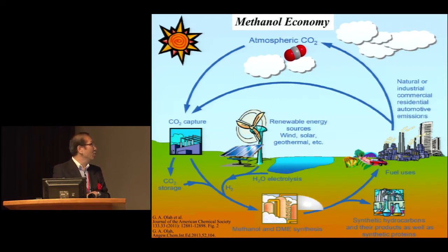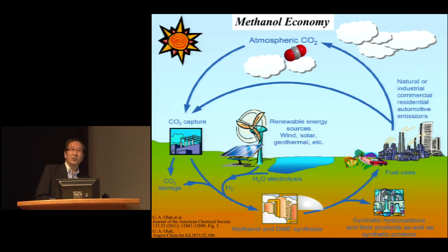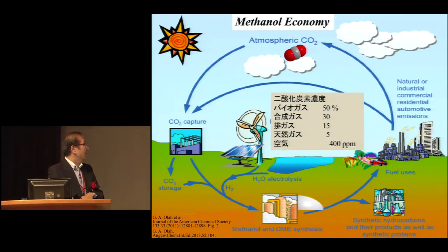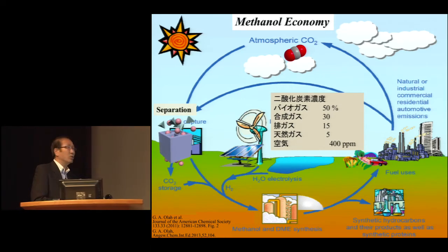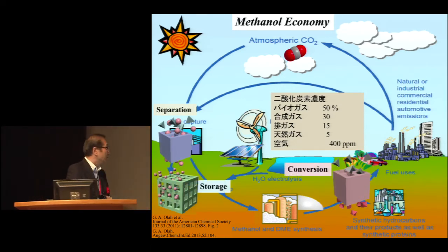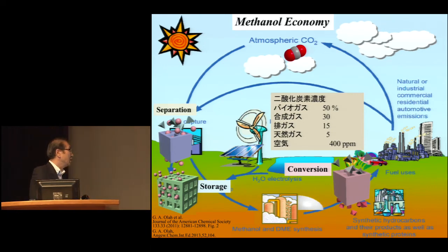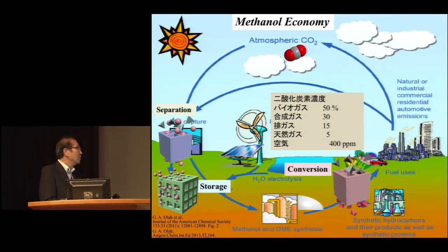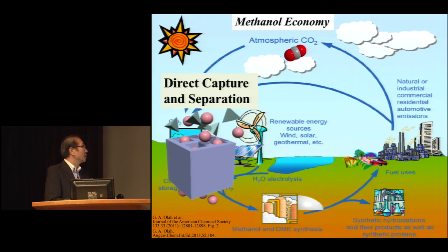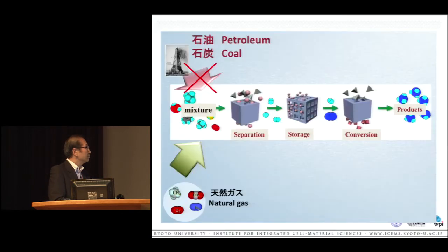And the methanol is the basis for various fuels and chemicals. Once they are burned, they go back to the atmosphere. But by repeating the same process, you can capture the material again. So this is a dreamlike society in the future. And biogas has a CO2 concentration of 50%, while the atmosphere is only 400 ppm in terms of CO2 concentration. But by using the porous material, we would enable direct capture and separation of CO2. And the catalysts are widely developed, and by joining them with the catalyst, we can realize direct capture and conversion.